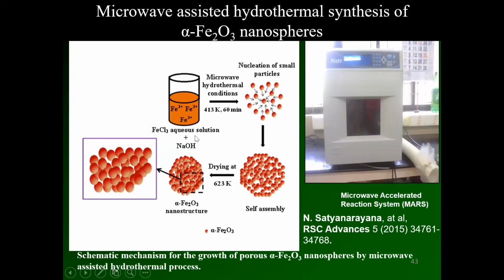So we have developed porous iron oxide. When you dissolve this, iron and chloride ions form in the solution. The solvent absorbs the microwaves and gets energy, and the movement of the ions generates heat because of friction. That heat energy is equivalent to what we provide by direct heating in the combustion process. Then a reaction takes place under particular conditions, and accordingly your compound forms. If you add a directional aid, you can change the shape of the material. Here it is a porous sphere type.